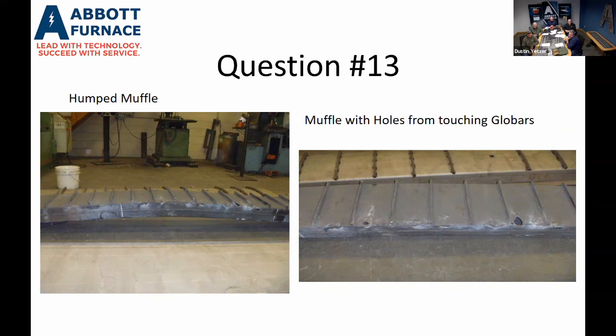So basically they ramped that muffle from 0 degrees to 2000 degrees in a matter of hours. They bowed it up, and it bowed so bad, if you could see on the second picture, the holes burned in the top of the muffle and on the side there. Those are from the glow bars of the heating elements, where the muffle grew up and actually hit the heating elements and burnt those holes in it.